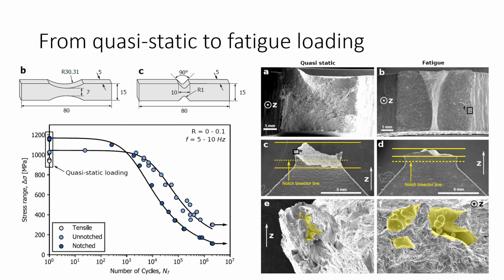And then we tested going from static loading to fatigue loading in order to see the trend. And so we see that somewhere within the low cycle fatigue range, we have a transition from notch strengthening to notch weakening. We can also see the difference in the fracture surfaces, where in A and B is the fracture surface and C and D is the front view of the fracture surfaces.